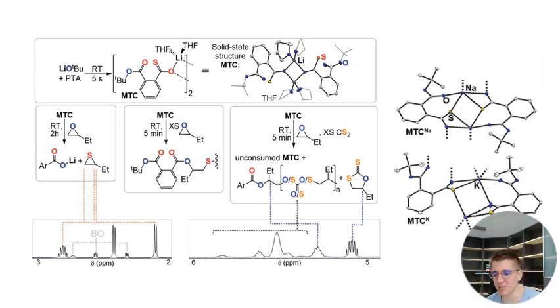And it's a reasonable hypothesis that when you move to softer alkaline metals, they start coordinating the sulfur. And so my hypothesis at the time was that the sulfur is maybe less free, more encumbered, to propagate for heavier alkali metals, which makes the catalysis slower or deactivates the polymerization altogether. This was the hypothesis, right? I mean, we did not go on and study this with density functional theory. It's as good as it got at the time.